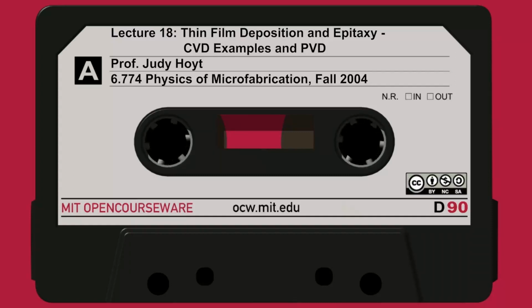Tungsten is used to fill plugs. It's often put down by low-pressure CVD using WF6, tungsten hexafluoride. Ti silicide can be put down in a couple different ways. It's usually sputtered. The titanium is usually sputtered initially, and then it's reacted.